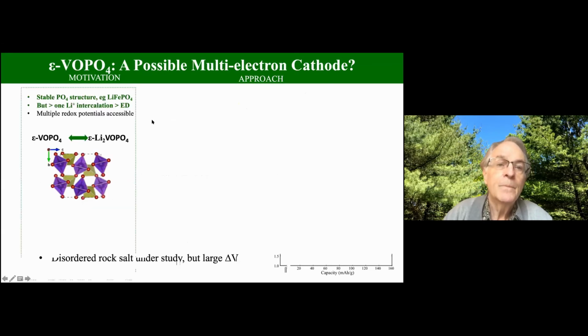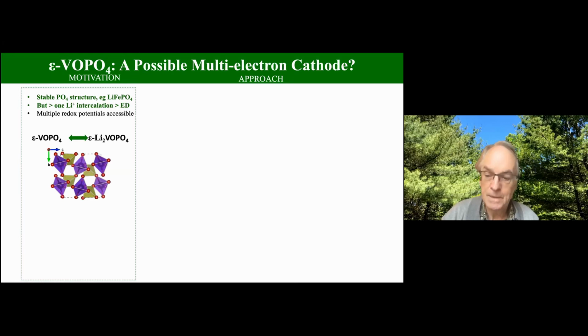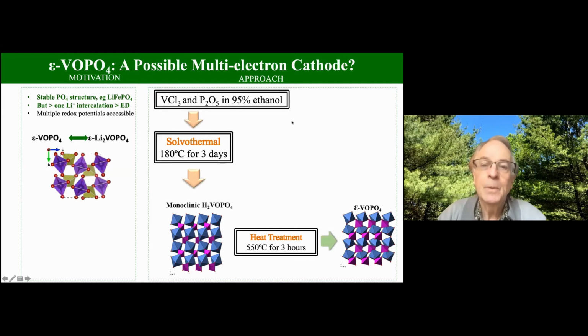So let's look at this vanadium phosphate material. This is a 3-dimensional structure with tunnels in all 3 directions. Alan Jacobson at Exxon was the first person to work on this, and he was interested in oxidation catalysts. After a lot of study, we were able to make good material of this phase by a solvothermal process where we reacted vanadium trichloride and phosphorus pentoxide in 95% ethanol. You have to have a little bit of water there, or the ethanol will reduce the vanadium trichloride too much. It just needs about 3 days reaction. I believe it's possible to do it in less. After that, you form this vanadium phosphate phase with hydrogen in the channels. A mild heat treatment removes all the hydrogen, and then you have your empty crystalline lattice.